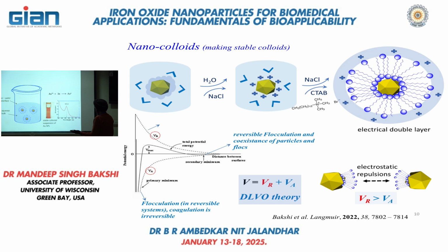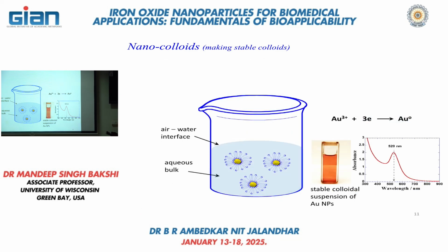So this is the solution you made yesterday by adding SDS. Now each nanoparticle has a bilayer of the surfactant, and as you see, you have the bright blue reactor, and that provides you the absorbance sharply close to 520 nanometer. So this was the story for the gold nanoparticle.